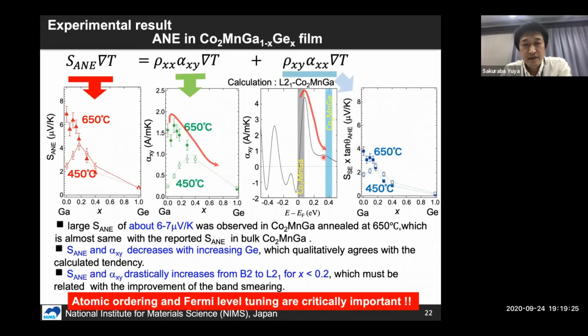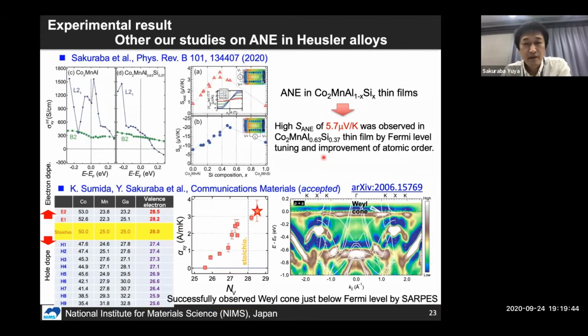So this kind of experimental and theoretical work tells us that atomic ordering and Fermi level tuning are very important to realize a large anomalous Nernst effect in cobalt-based Heusler compounds. Okay, here I showed several other studies of ours on the anomalous Nernst effect in Heusler compounds.